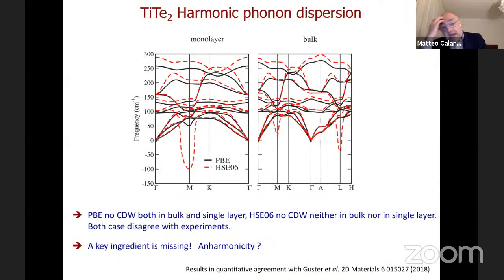Now what happens if you calculate the harmonic phonon dispersion in these two systems? As I told you before, we take the 1T phase, the phase with no distortion. In the bulk, the 1T phase is stable everywhere. In the monolayer, on the contrary, the 1T phase is unstable. We calculate at zero temperature its phonon dispersion. And what happens is very funny, because in PBE there is no instability neither in bulk nor in single layer.